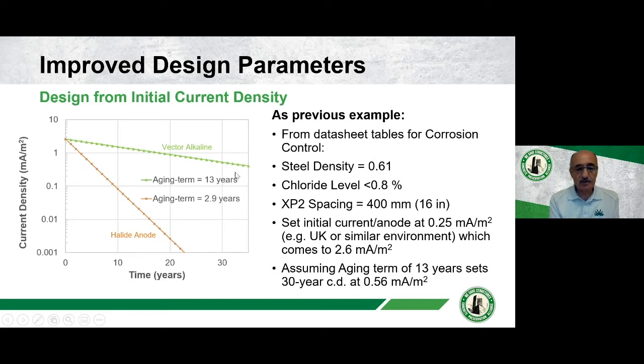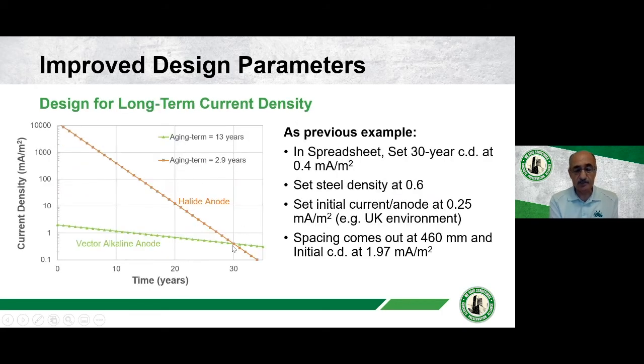If, however, we use a different anode, which has a different aging term, and I know that halide anodes, for example, have a much lower aging factor, aging half-life of less than 3 years. If you start with the same current density, you will see that very quickly that current is going to drop to levels that are not really usable anymore. So you need to reverse that process, really. You have to start from your 30 year and assume that this is the current that I want, and I've got to work out backwards.